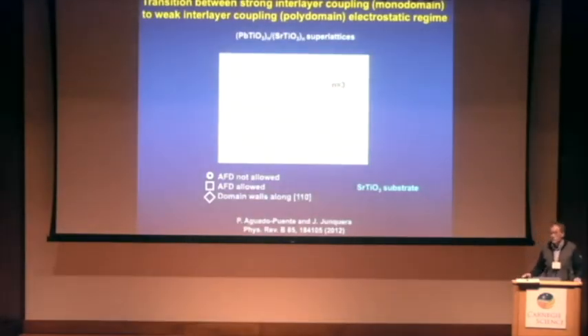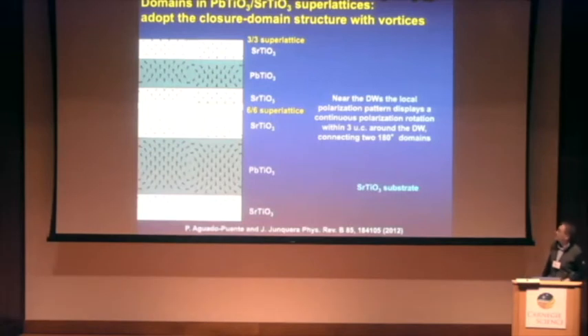So a few years ago, we started to do some first principle calculations in this kind of lead titanate, strontium titanate superlattices, and essentially we were able to corroborate all these arguments. In particular, for a periodicity of 3 unit cells of lead titanate and 3 unit cells of strontium titanate, the ground state was monodomain, with the polarization pointing in this R phase, essentially along the 111 direction, while the domain structure here, we were able to stabilize the domain structure only as metastable phases. However, if we increase the number of unit cells from 3 to 6, then the domain structure becomes the most stable one, and they adopt here the shape of one of these domains of closure. So when the polarization goes from up to down, there is a continuous rotation of the polarization around 3 unit cells around the domain walls here.